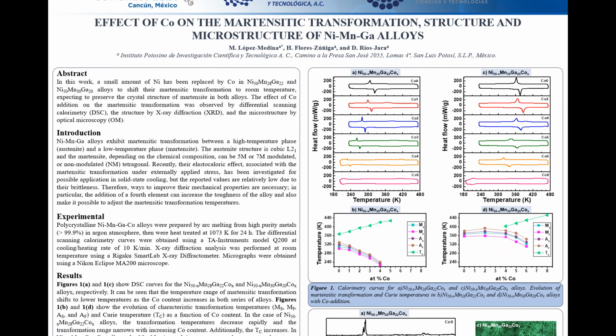In this work, a small amount of nickel has been replaced by cobalt in Ni50Mn28Ga22 and Ni50Mn30Ga20 alloys to shift their martensitic transformation to room temperature, expecting to preserve the crystal structure of martensite in both alloys. The effect of cobalt addition on the martensitic transformation was observed by differential scanning calorimetry, the structure by X-ray diffraction, and the microstructure by optical microscopy.